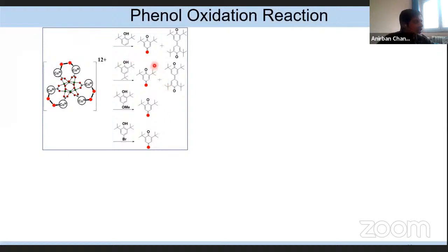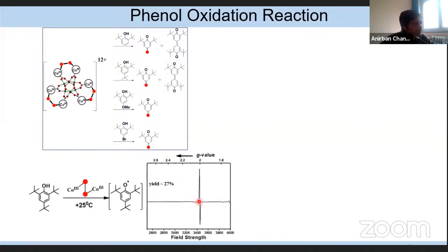Okay, now to find out more details about the mechanism, I did the product analysis with normal oxygen and also 18O labeled oxygen, and I found that in almost every case 1,4-benzoquinone is the major product, and for 2,6-di-tert-butylphenol and 2,4,6-tri-tert-butylphenol, we also found the diphenoquinone product. For the reaction with 2,4,6-tri-tert-butylphenol, at the end of the reaction, I also get an EPR signal with g value 2, which indicates the presence of a free radical of the 2,4,6-tri-tert-butyl radical system.